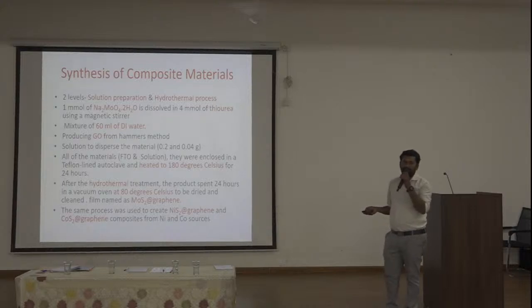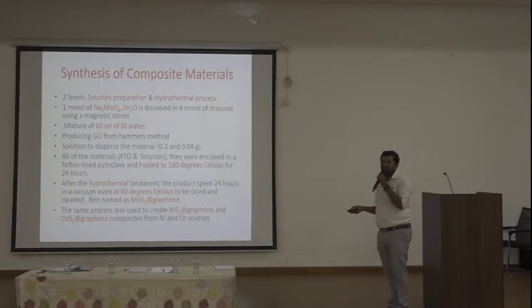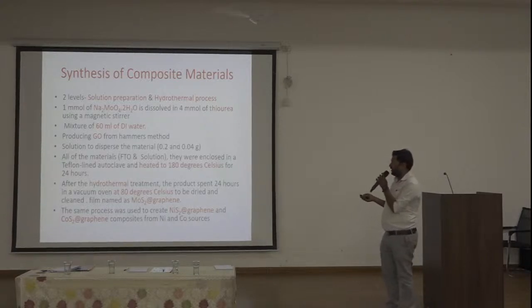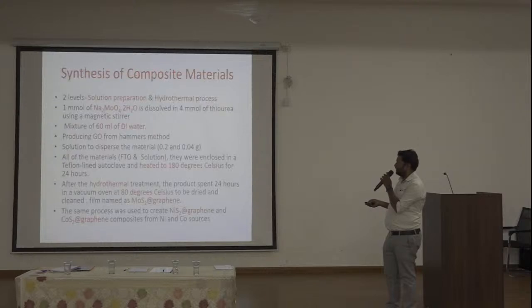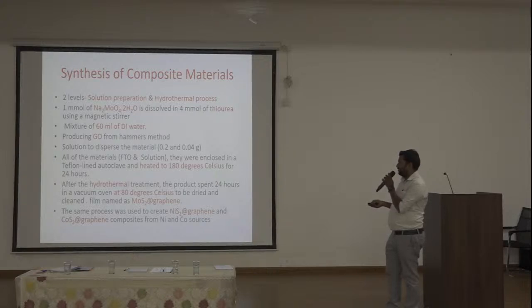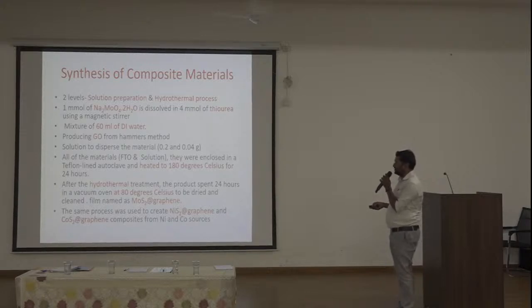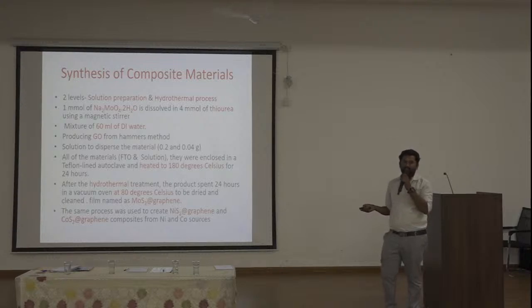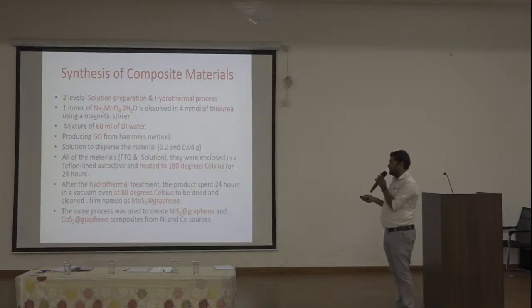So the synthesis of the nanocomposite material has two different stages. The first one is solution preparation, and the second one is the hydrothermal process. We can prepare the solution with sodium molybdate and thiourea, adding 60 ml of deionized water, and also preparing the graphite oxide with the Hummers method. Another process will be the hydrothermal, which will be at 180 degrees Celsius for 24 hours. So this film is named molybdenum disulfide with the graphene. And for the other samples, we can change the materials to nickel disulfide and cobalt disulfide with the graphene.